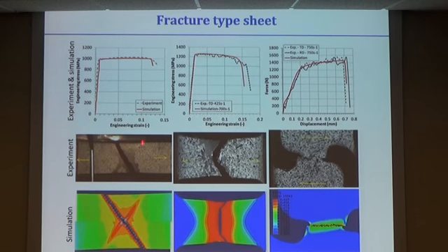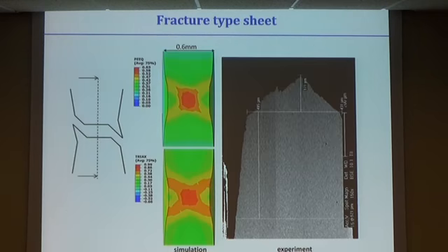For the small Hopkinson samples, we also found combined fracture types: slant fracture in the middle, more on that later, and also the bands according to the localized length. For the dynamic shear, we also captured the fracture as we had in the experiments.